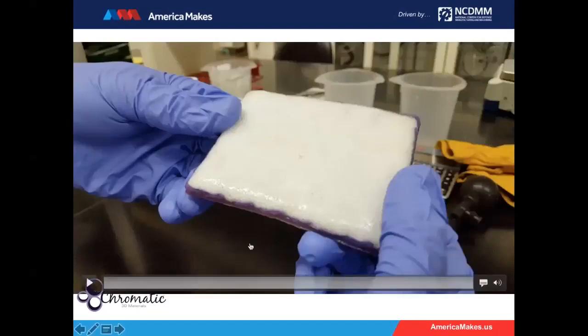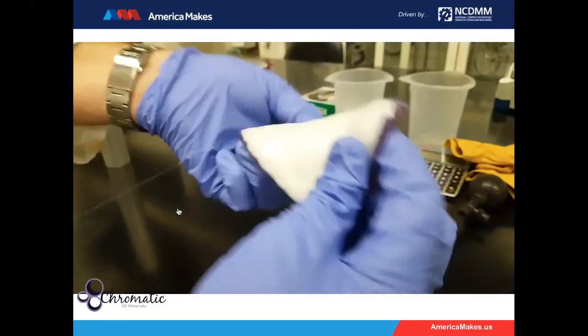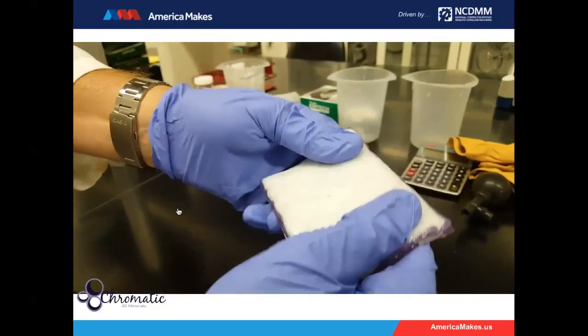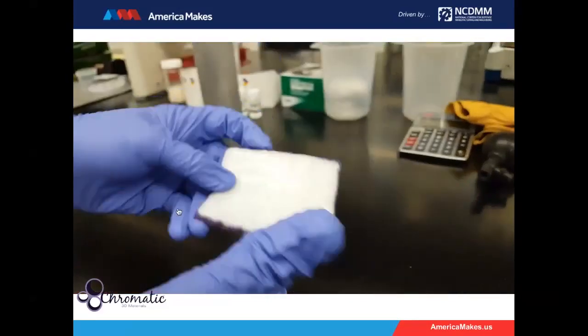Taking this a little bit further, as I mentioned at the opening, thermosets and polyurethanes could be used to make foams. And so this is an example of where we've got a printed elastomer base with an embedded foam. So here's an example of what that can look like and what kind of design that can make. So we have a very flexible part, and the foam, if you could touch this part, the foam feels quite soft and comfortable, and yet when we pound on it, it's still very, very strong because that elastomeric network can provide support. So this is really just being able to integrate parts in a way that could only be done with some of the most complex injection molding technology we're able to bring to bear in 3D printing.